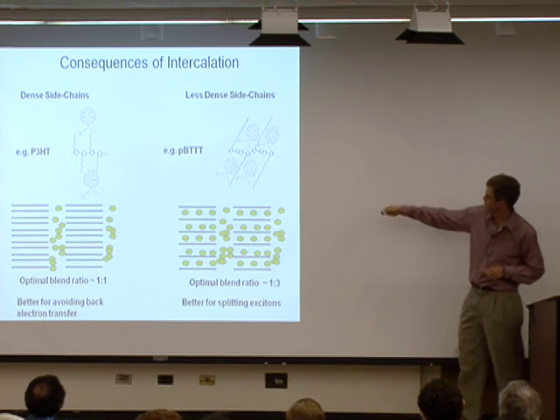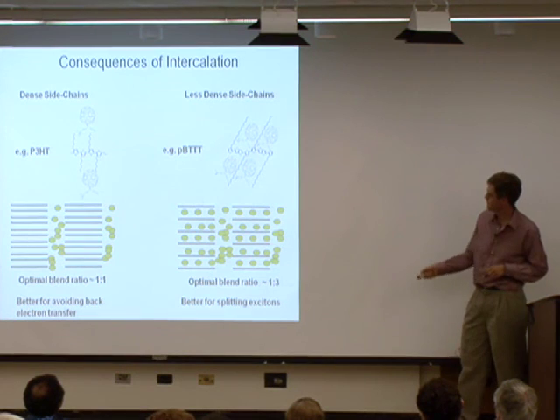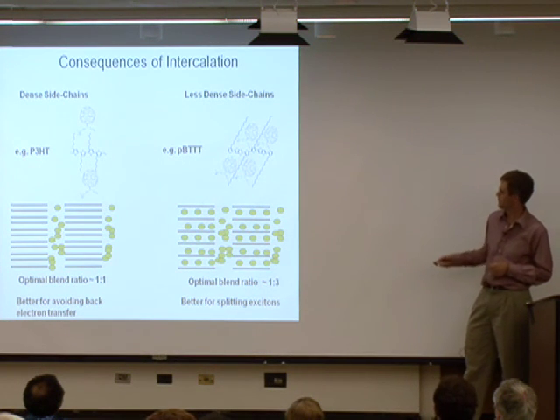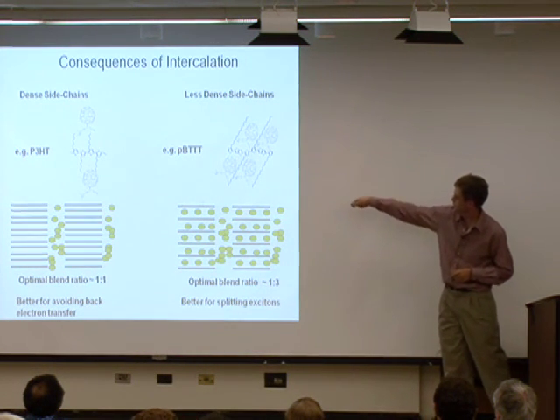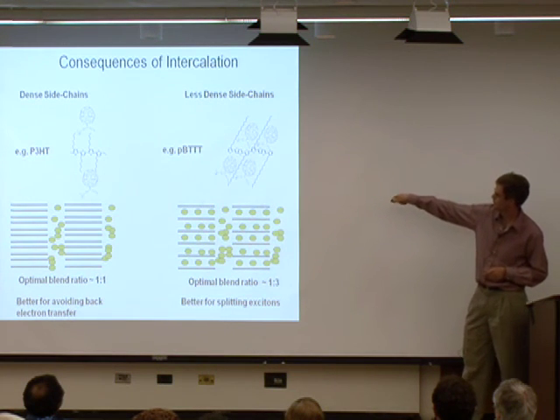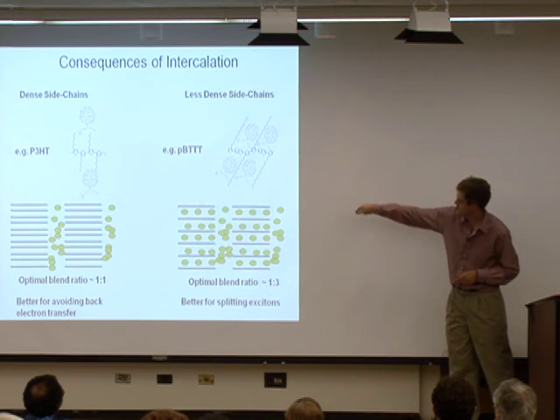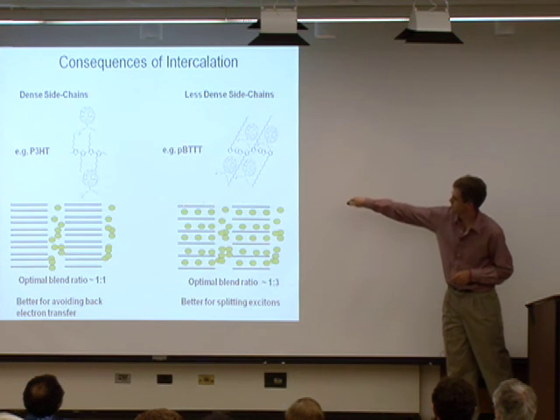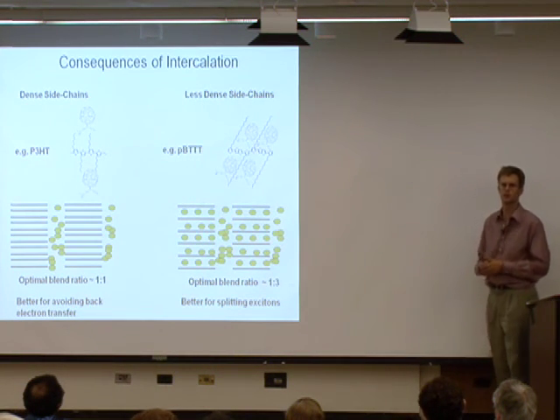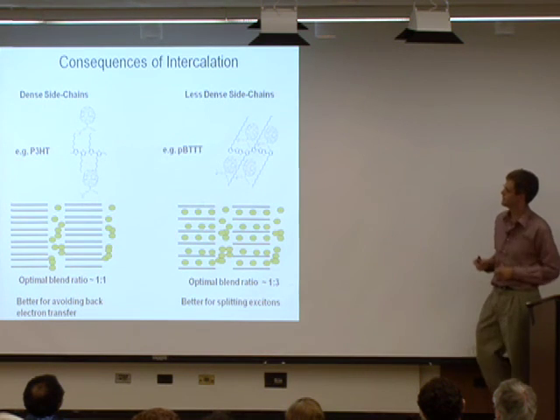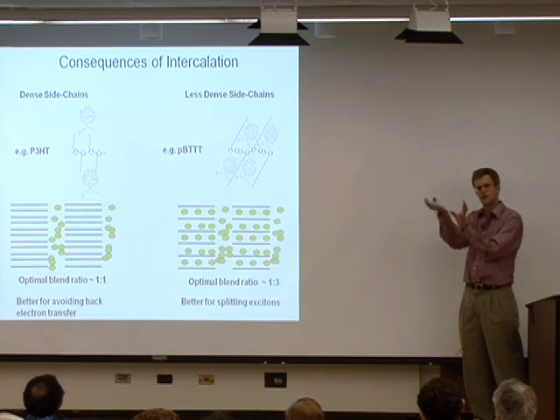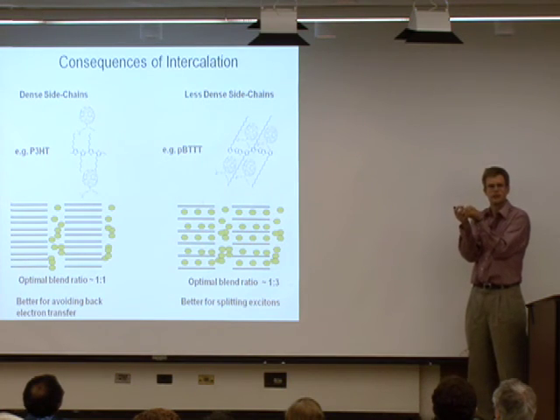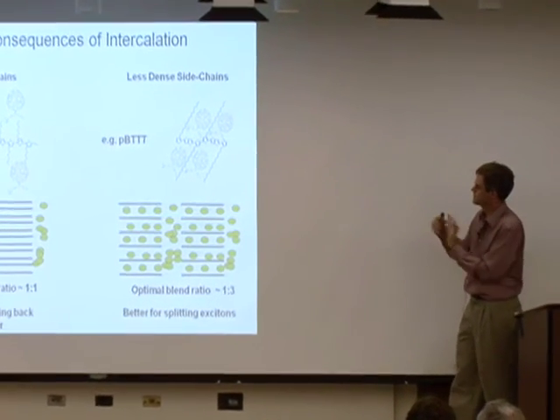But when the fullerene goes in between the side chains, then you need about a 1-to-3 blend, because you need 1 part to mix in with the polymer, and then you need 2 parts so that there's this pure electron transporting phase that matches the volume of the hole transporting phase. And if you lose that balance, then one of the phases can surround the other phase and confine charge carriers in there. So that's just an example of what our team is able to learn by using our advanced characterization techniques.